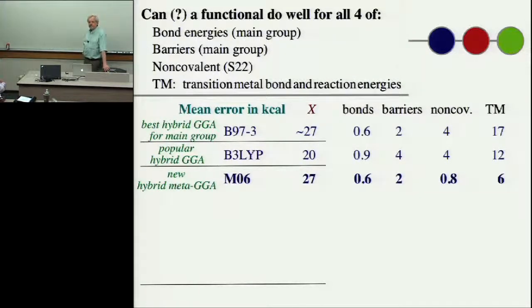JJ. For the standard GGA versus LDA, people say that the GGA overestimates the static volume and LDA underestimates a little bit. How about you? This is new for the solid, for the mineral solid? Well, we've done a limited amount of work on solids, but we seem to get very good lattice constants with M06-L and with SOGGA, which is not a general purpose functional. But we seem to get very good lattice constants. We seem to get excellent geometries for both solids and molecules with M06-L. And with M06, they're almost as good. As good as M06-L, which in one paper we wrote, M06-L had the best performance for solid state lattice constants.